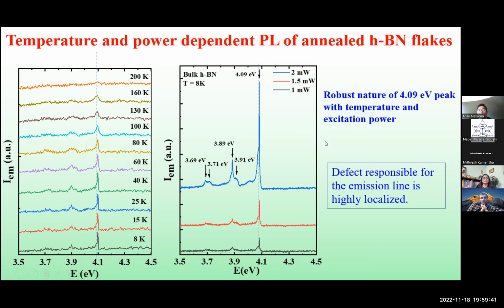This other graph is for different excitation power. We measured the photoluminescence at 8K, but applied different powers of the laser light, changing the intensity. As we increase the intensity, it also increases the intensity of this emission peak. That's obvious, but the energy peak position remains the same.